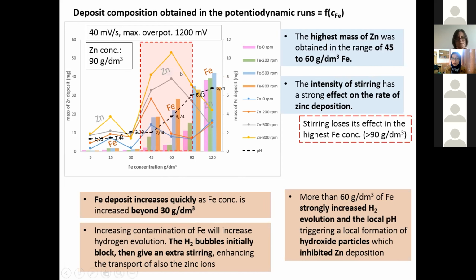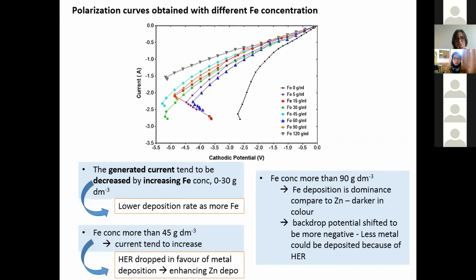So if our goal is co-deposition, this condition is good to be done. But because our goal is purity, we need to remove the iron before the electrodeposition stage. And here is the result of the current pattern when we do the electrodeposition.